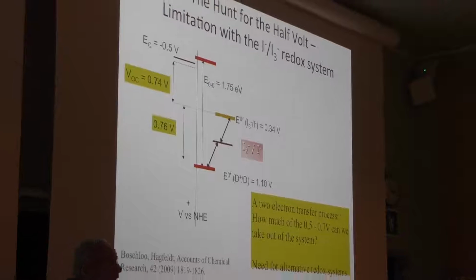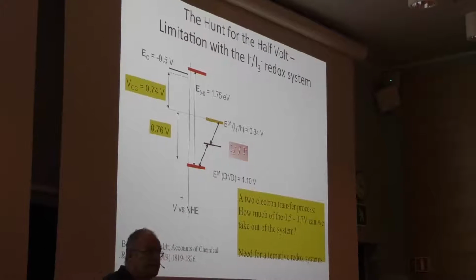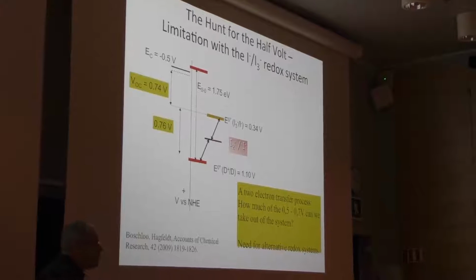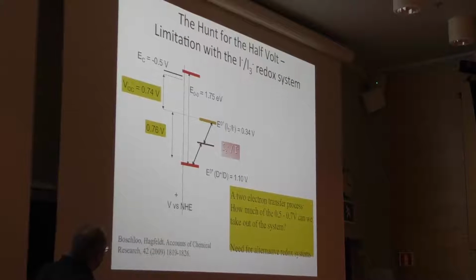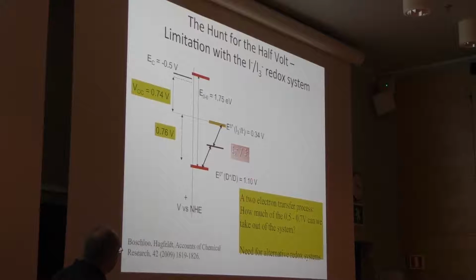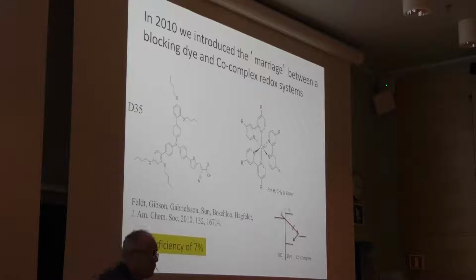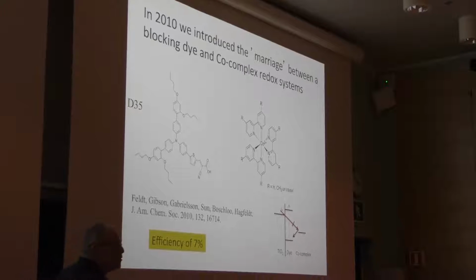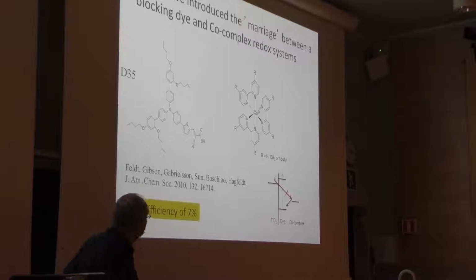And there have been a lot of tries to have insulating aluminum oxide, zirconium oxide and so on on the surface, but not very successful. But our conclusion here in 2009 was that if you really want to have a new breakthrough in efficiency, we do have to change the electrolyte and to passivate the surface. So we started that as a PhD program, but we knew it was very challenging. But we had a piece of luck, I must admit. This was not really planned, as often in science the big discoveries are not really planned.